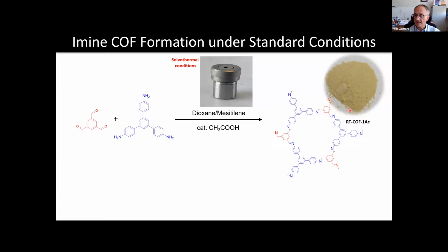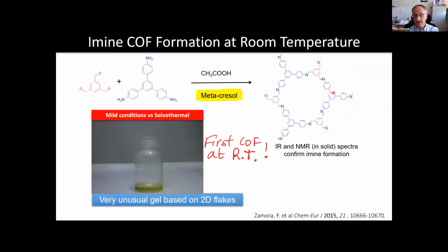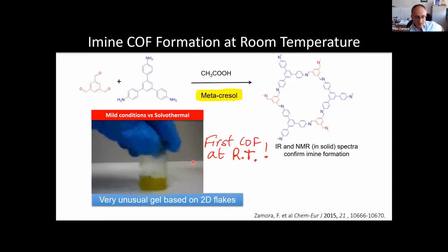And this powder for many applications is useless. But look here, when you combine the same building blocks and you change just the solvent, and we use, for instance, metacresol or DMSO, and then you incorporate the catalyst, you will see we have the solution with the two initial components in metacresol, we incorporate the catalyst, and you will see that within a few seconds you will end up with the formation of a gel. Okay, here we go. So we form this gel.